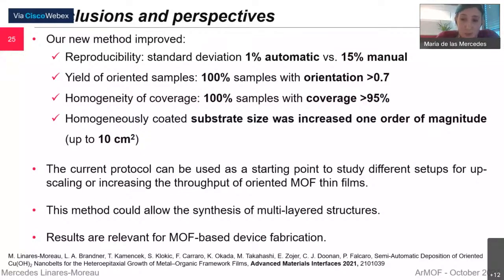This is interesting because, as I talked about before, the quality of the copper hydroxide substrates impacts directly on the quality of the MOF film. So this could allow increasing the throughput of the fabrication of oriented MOF thin films, and could be used for multi-layer structures and be interesting for MOF-based device fabrication.